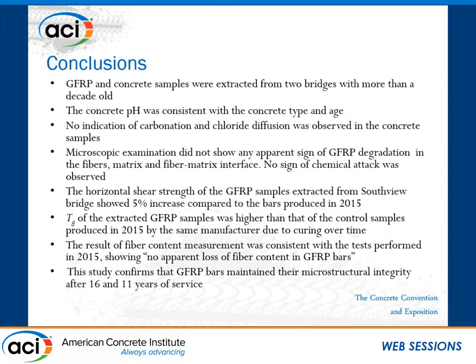First, the concrete was tested, and the pH was in the expected range. No carbonation and no chloride diffusion were observed in the concrete. Next, different mechanical tests and microscopy examination were performed to provide evidence of the durability of this material. The microscopy examination did not show any sign of GFRP degradation nor any sign of chemical attacks on these materials.